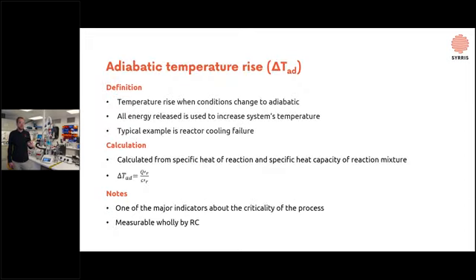So it's the temperature rise when conditions change to adiabatic. What happens if the conditions change to adiabatic? As I mentioned with the adiabatic calorimeters, most of the heat released by the reaction will be contained inside, resulting in a temperature increase. A typical example where a reactor can enter this kind of mode is when a cooling failure occurs. It's calculated from the specific heat of reaction and the specific heat capacity of the reaction mixture. And it's one of the major indicators of the criticality of the process. We'll touch on that a little bit later.